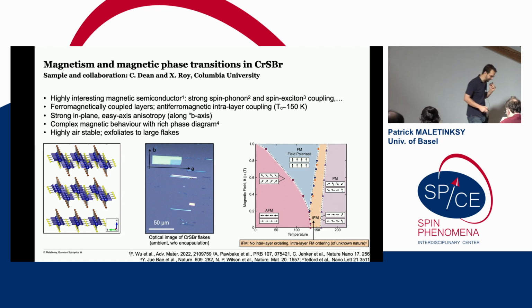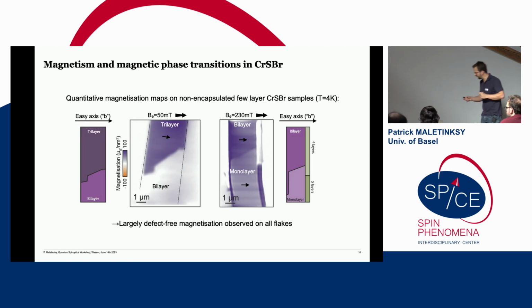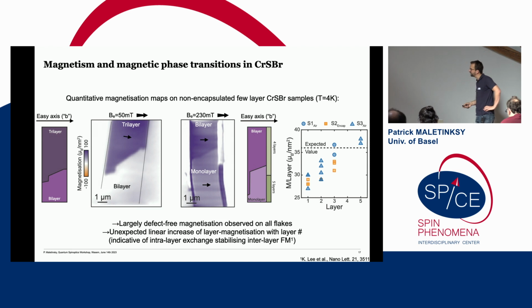Okay, so we looked at this material for all these reasons. Here are some data, and I show you now all these reverse propagated images and not the bare NV magnetometry, just for clarity. So here are a couple of flakes again, bilayer, trilayer, monolayer. You see all of them show a magnetization. The bilayer, again, of course, zero magnetization at low field, but we can flip it into a fully polarized state here by applying a field. And that gives us, in all cases, a magnetization in quantitative units, and we can then plot this, essentially the magnetization per layer as a function of the layer number in these samples.